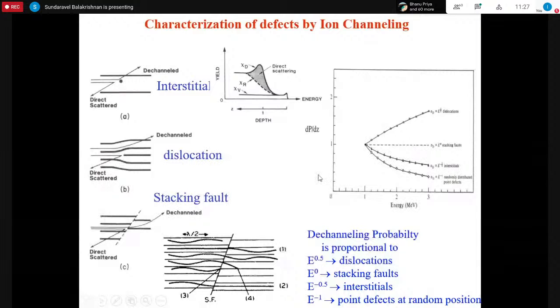And if you plot the dechanneling probability as a function of energy, each type of defect will have a different energy dependence. For example, for dislocations, we cannot tell whether it is vacancy type or interstitial type, but we can tell there is a dislocation, and there is an energy dependence of E to the power of some exponent. If stacking faults are there, there won't be energy dependence, or for vacancies also no energy dependence. For interstitial defects, there will be E to the power of a negative exponent. When point defects are at random positions, then it will be E to the power minus 1. So by seeing this energy dependence as well as these slopes, we can tell about this type of defects and how it is sensitive to point defects.